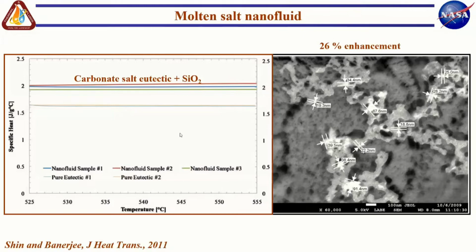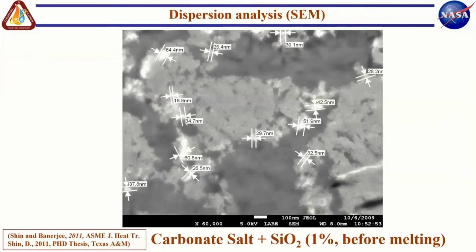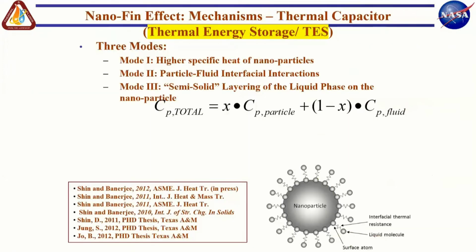So on the left, you see the bottom line, blue and orange, is pure molten salt. And the moment we add 1% by mass of silica nanoparticles, which are about 50 nanometers in diameter, nominally between 20 and 60 essentially, the heat capacity goes up by 26%. And we think that it's because of this compressed layer that forms around the nanoparticle. So in the interest of time, let me switch.